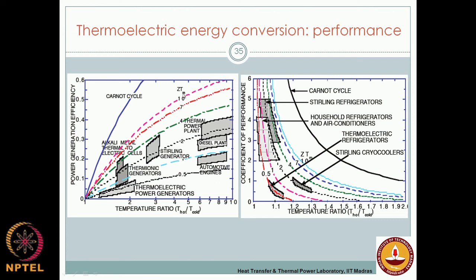So, here these are all plotted for different values of figure of merit. The figure of merit of all these thermoelectric devices is typically very low, and therefore, if you compare to your thermal power plants which have efficiencies of the order of 30 to 40%. Okay. So, these suffer from low thermal efficiencies. Okay. However, they are very clean energy sources.